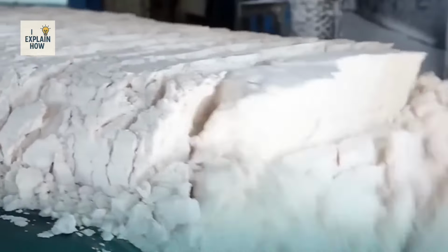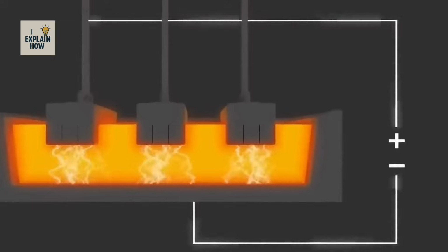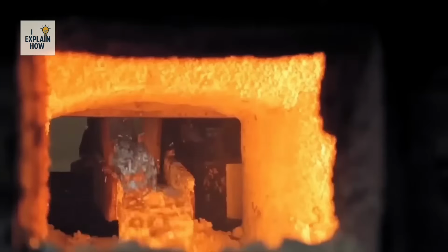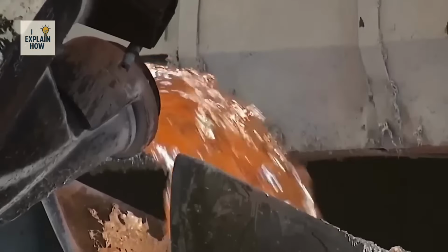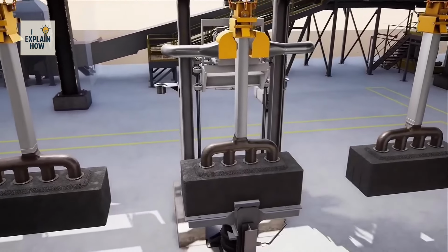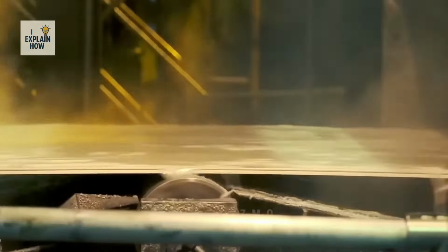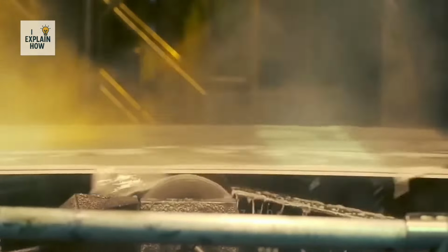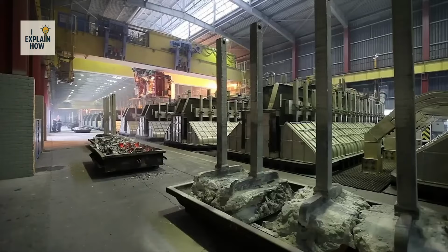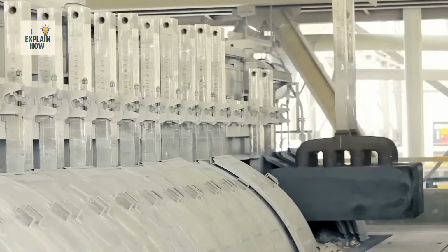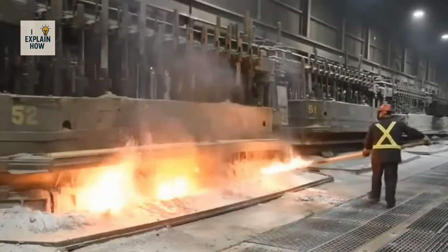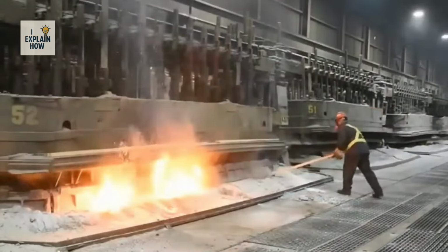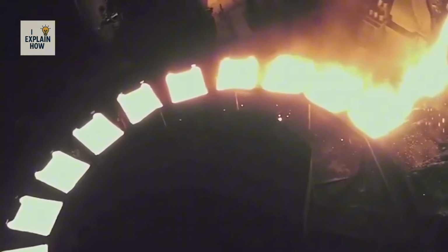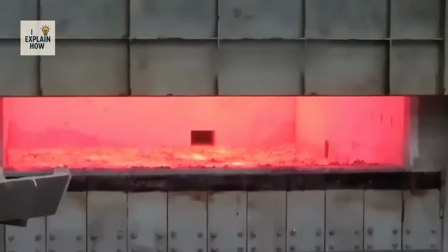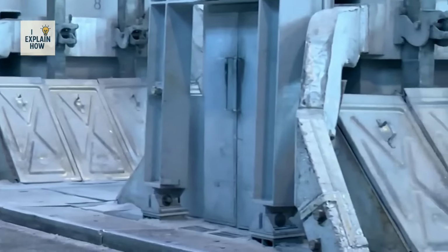The material is then deposited onto conveyor belts and transported to the plant where the alumina is introduced into large electrolytic cells filled with molten cryolite. Cryolite lowers the melting point of alumina from 2050 degrees C to about 950 degrees Celsius. To obtain pure aluminum, it is necessary to separate the oxygen atoms that hold it tightly together. This process requires enormous amounts of electricity. That is why aluminum is called electricity in solid form.